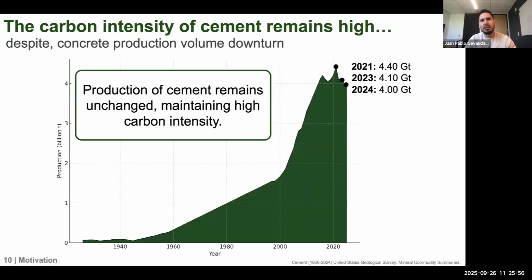But what we see is that the reason why those CO2 emissions have decreased is actually a concrete production volume downturn, particularly for the Chinese real estate market. And what we see is that we're producing around 4 gigatons of concrete from last year, and that's where we're stabilizing, and that's where we think we're going to be stabilizing for at least a couple more years. Now, the key takeaway here is that the production of cement remains unchanged, and that's why we're maintaining that high carbon intensity in cement production. So we really need to be thinking about how we're actually going to decrease that cement carbon intensity.